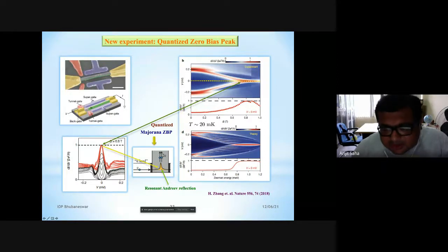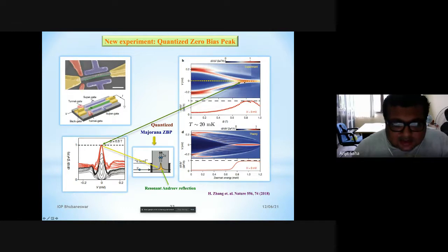Here also in the 2D plot it is the same. In the trivial regime, there is no signal. You change your magnetic field such that you enter into the topological regime, where it behaves like a Kitaev chain. I have a pairing and the Majorana signature coming out as this 2e squared over h. So this is the indirect signature. The zero bias peak can come from other reasons also, but at least they claim, by arguing that the other reasons are not possible in the experiment, that this can be an indirect signature of the Majorana. And these experiments are done at very low temperature, like 20 millikelvin.